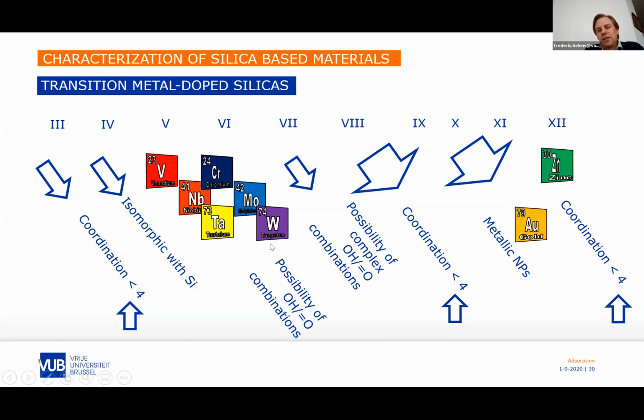Then we have groups 5 and 6 that I showed you before. There we have especially the competition between hydroxyl groups and oxo groups. The same for group 7, which we have not studied yet, but there we increase the possibility. Imagine that we have manganese 7, then we can even go further with the number of hydroxyl groups or oxo groups. Then we go down again in the coordination for group 8, lower than 4, so we will have defects. I expect that these sites can provoke defects in the silica. And then we have the noble metals, the coinage metals, which form nanoparticles, mainly gold. We have done the study for gold. And then the zinc that I've just shown you. So this is about our study on heterogeneous catalysis.